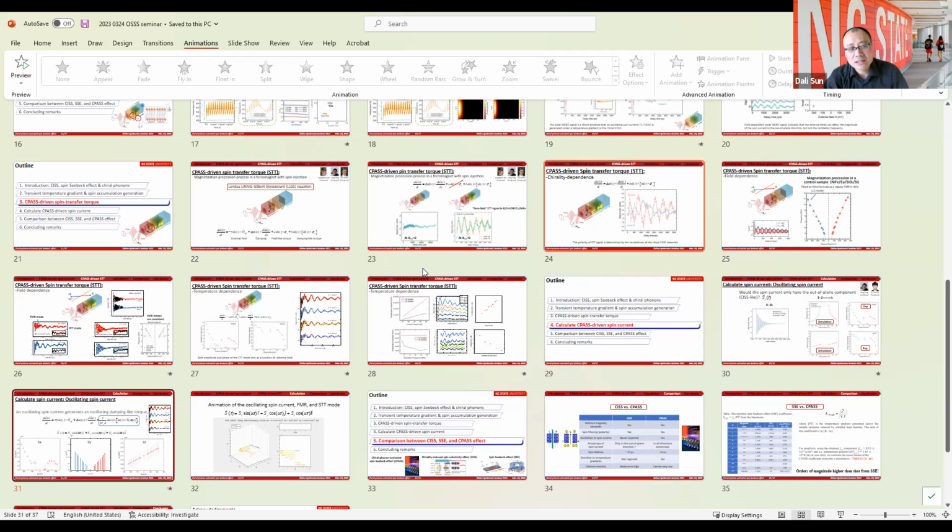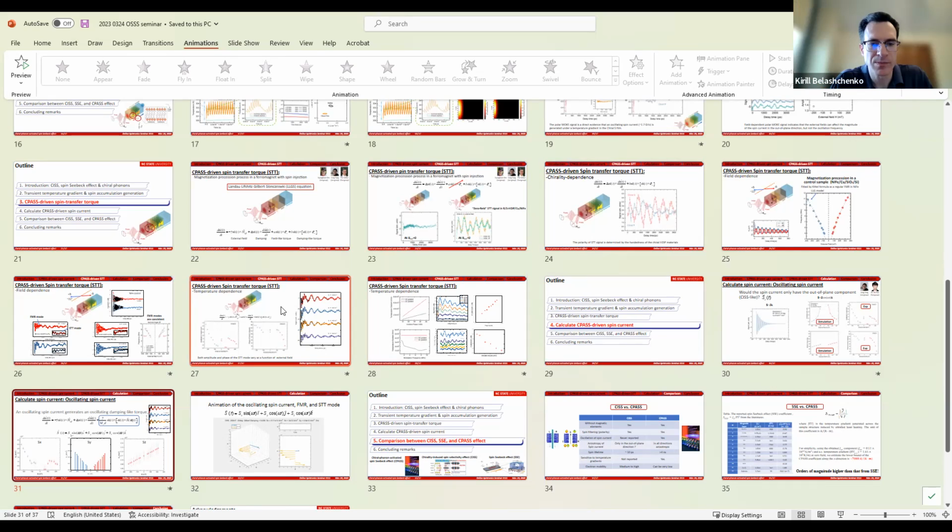We validated the nickel iron's intrinsic properties with the field dependence. The field direction is around 22 degrees away from the normal direction, and we got results very consistent with the FMR mode the nickel iron is supposed to show. The nickel iron is supposed to be in plane, right? It's just 15 nanometers of ordinary nickel iron, and the anisotropy is still in plane. We apply a magnetic field slightly tilted, 22 degrees away from normal, and you can also fit very well with the Kittel equation at 22 degrees. It fits the normal FMR mode for nickel iron.